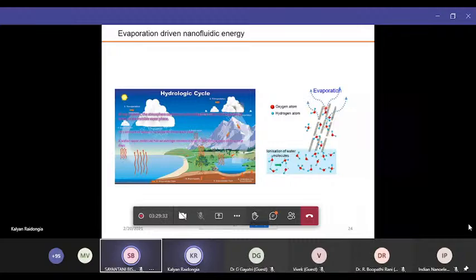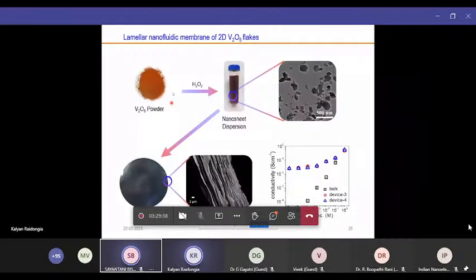Okay, for that we again took help of the 2D nanomaterials, where for a proof of concept we prepared vanadium pentoxide sheets by using hydrogen peroxide in ice cool conditions. Then we can prepare a freestanding membrane. These are the channels, and this surface charge governed ionic conductivity curve shows that we actually have well-defined nanofluidic channels in this layered material, with so many channels in it.